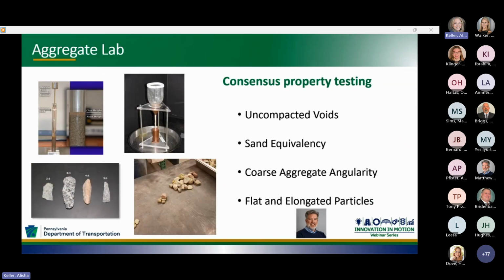Here is some of the consensus property testing we do. Uncompacted voids measures the loose void content of fine aggregate to assess its angularity, sphericity, and surface texture. Higher void content indicates more angular particles, which provides interlocking and stability in asphalt pavement mixtures. Sand equivalency measures the relative proportions of undesirable clay-like fines or dust in fine aggregate that can reduce performance of an asphalt pavement. Coarse aggregate angularity measures the percentage of fractured faces on crushed aggregate. Higher percentages of crushed particles are needed to improve interlocking and reduce deformation in asphalt pavements.